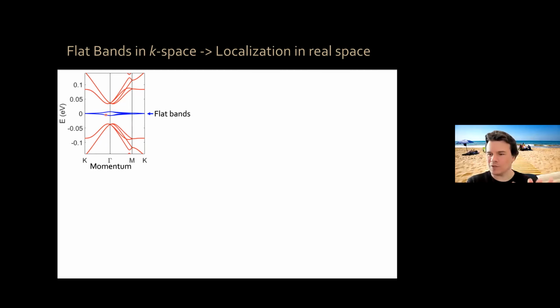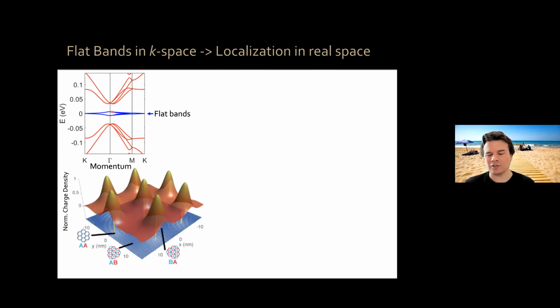Where do they like to go in real space? Now, to go from momentum space to real space, you have to do a Fourier transform. So flat in momentum space means highly localized in real space. If you calculate when you put electrons in these flat bands, where do they like to sit? It turns out they like to sit locally in regions where the two graphene sheets locally look like all the carbon atoms are on top of each other. These are regions of AA stacking locally.